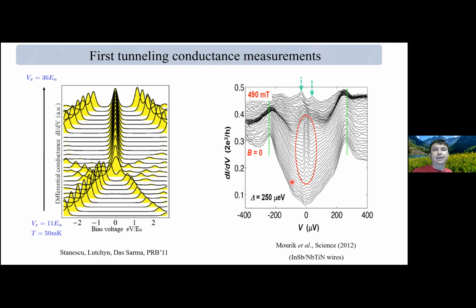And here's the data that was obtained by the group, and here are basically results of some previous simulations. The simplest thing one can test in order to test this theory is to see that upon application of a certain magnetic field, we have zero energy states in local tunneling conductance. So indeed, when they exceed some critical field, there is a zero energy state appearing in tunneling conductance, which is consistent with the Majorana scenario.